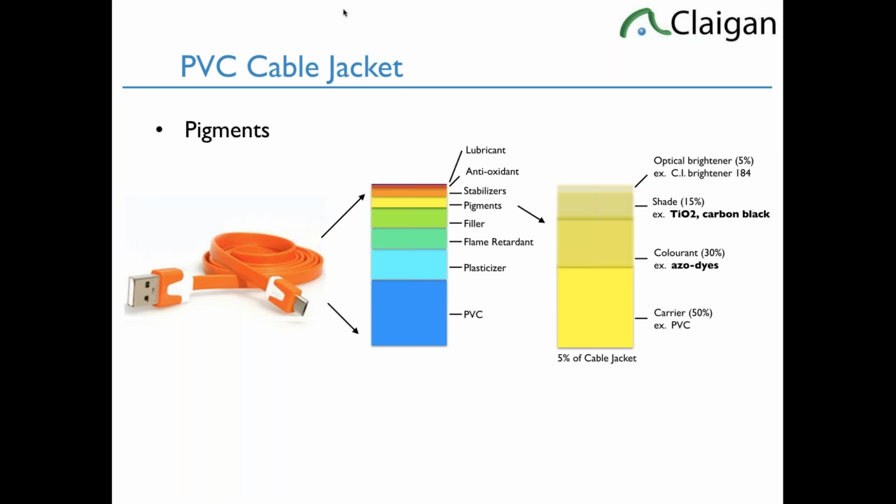Cobalt is not an uncommon source of blue or green in plastics. And people might be worried about, I now have a blue medical device, it's got cobalt in it, I have a CMR. It's cobalt metal. The cobalt normally used as a dye in PVC or otherwise is something like blue 36, which is really a cobalt aluminum chromium oxide spinel. It's a different chemical. It's not cobalt. So even though cobalt is creating the blue, it's actually a cobalt aluminum chromium oxide chemical. It's a very different chemical than cobalt itself, which is elemental.